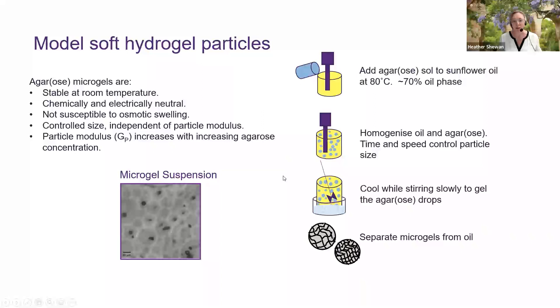Can we look at all this based on a fundamental model of soft hydrogel particles? I spent extensive time making model particles from agarose, which makes a nice model system because the particles aren't attractive — they're stable, chemically and electrically neutral, they don't shrink and swell with other ingredients, and I can tune their particle modulus just by changing the agarose concentration. We also made agar ones for sensory trials, though agar particles are a bit more attractive.